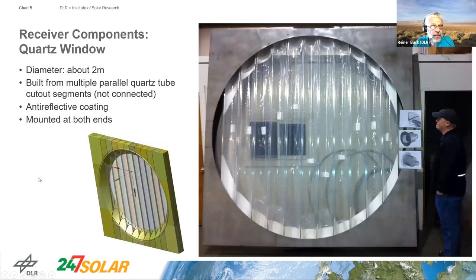Here are some images of some of the components. This is the quartz window, which is intended for operation with the receiver. It has a diameter of about 2 meters. So you see a person here standing beside the first prototype of that unit. It's built from multiple parallel quartz tubes, which are cut in the axial direction. And the segments are not interconnected. They are put very closely together, so there is nearly no gap between them. But they can more or less move freely one against the other, which helps to prevent the stresses which appear if you have very large, inhomogeneously heated surfaces.